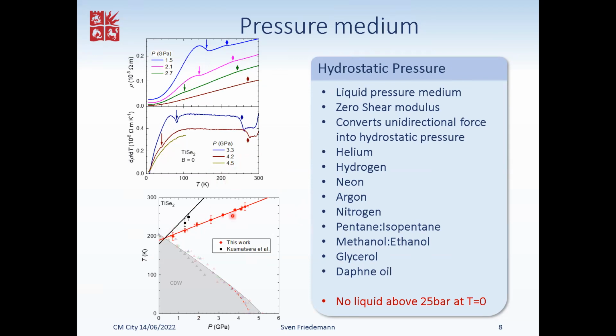So if we trace that through the phase diagram, it's a straight line with the zero pressure intercept being the freezing temperature of glycerol, the pressure medium used, and this intercept here at 5 GPa and 300 Kelvin being the solidification pressure, exactly known for glycerol. So sometimes one can see this, and some materials are more sensitive to this than others. You can probably easily imagine that a transition metal dichalcogenide, a van der Waals compound, is quite sensitive to any non-hydrostatic conditions in the c direction.